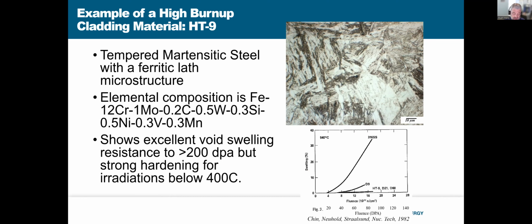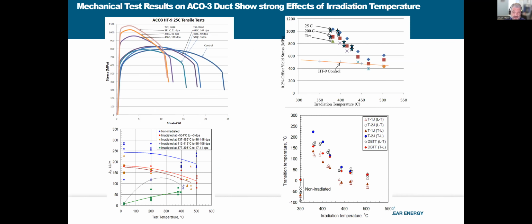So it does show good void swelling resistance, but in one of the studies, and others have shown this as well, you can see that there are some limitations also to HT9, and one is that it hardens significantly at lower temperatures. You can see this in a component that was tested after radiation in the Fast Flux Test Facility called the ACO3 duct. And there you can see a few things that are quite evident. One is that as you lower the irradiation temperature, so this is 416 here, 398 and 381, you get significantly more hardening in the material. And going along with that, you also get a reduction in the uniform elongation in this material as well.